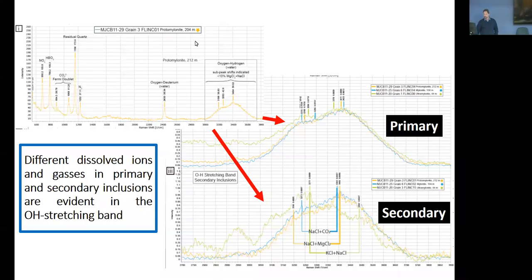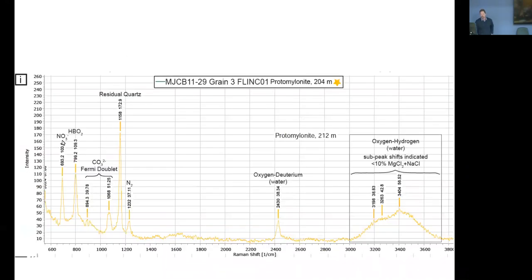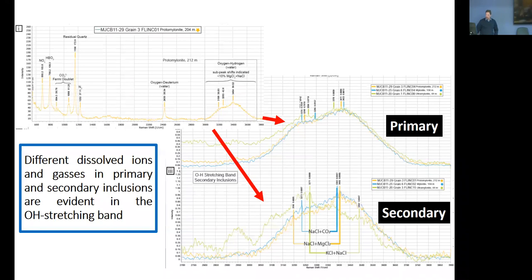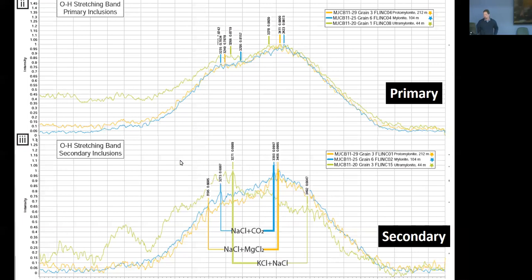So here are two spectra. It's a very broad spectrum from about 600 wave numbers all the way to 3,800. And then there's a zoom in. So let's zoom into the top one. They see typical spectra indicative of nitrate, carbonate, as well as quartz, which all makes sense. But what they were really interested in was this area here where you have the hydroxyl group information that comes out. And if we zoom into this area, I'm going to zoom in even a little more so you can see this better.